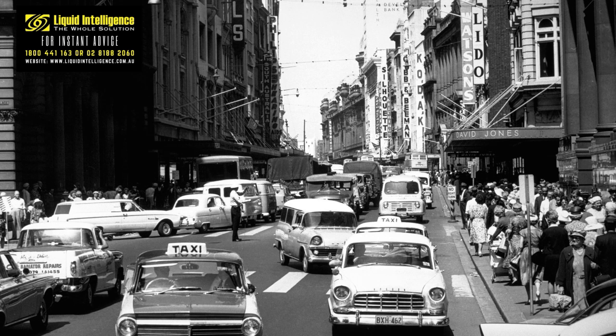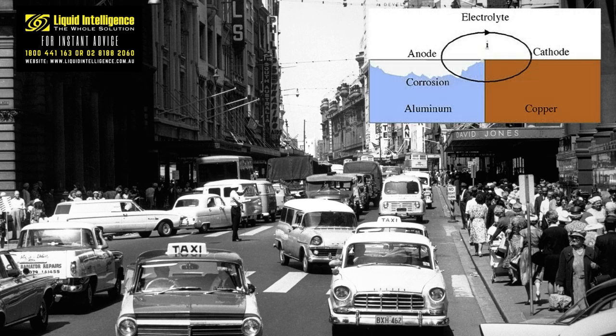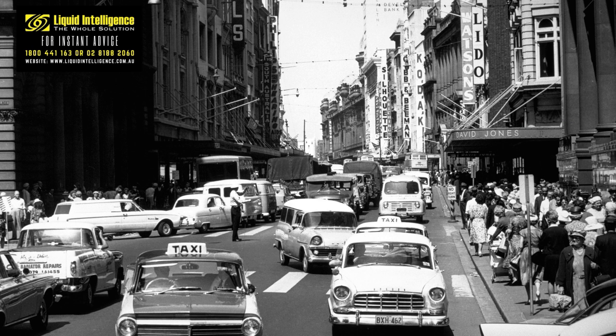However, ethylene glycol-based coolants were also found to be highly conductive electrolyte solutions. As such, they acted as both catalysts and conductors between anodic and cathodic metals in early automotive cooling systems, thereby causing galvanic corrosion. This issue was soon acknowledged as a significant concern by the automotive industry. Consequently, after the 1960s, vehicle manufacturers began designing cooling systems with anodic and cathodic metals positioned to avoid close proximity to each other, thus reducing the susceptibility to galvanic corrosion. Despite advancements in coolant formulations and cooling system design, most vehicles manufactured before the 1960s remained prone to galvanic corrosion when using ethylene glycol-based coolants.